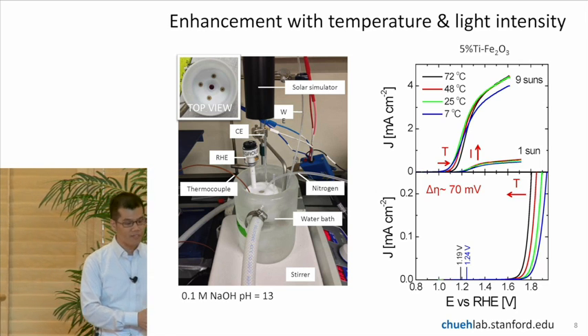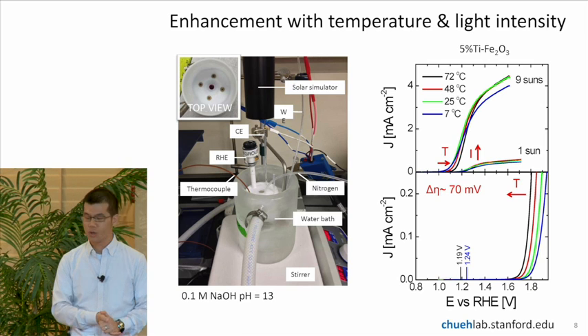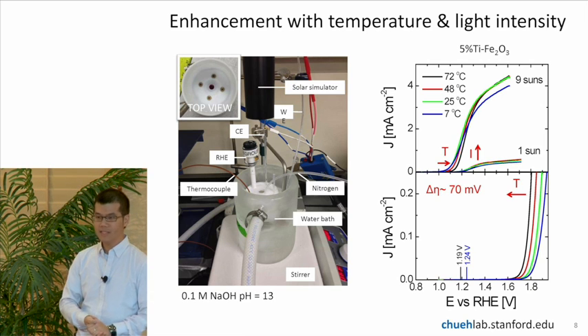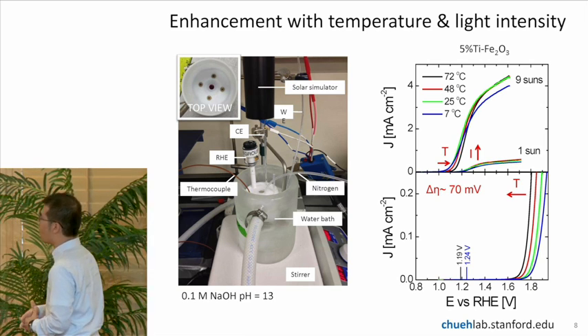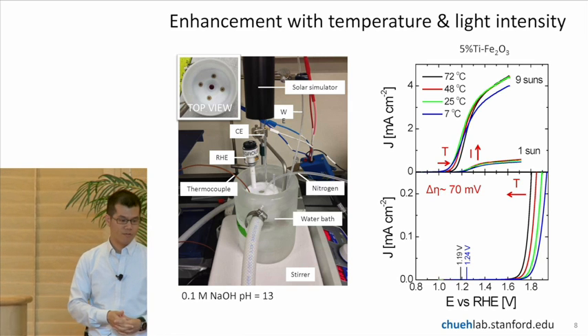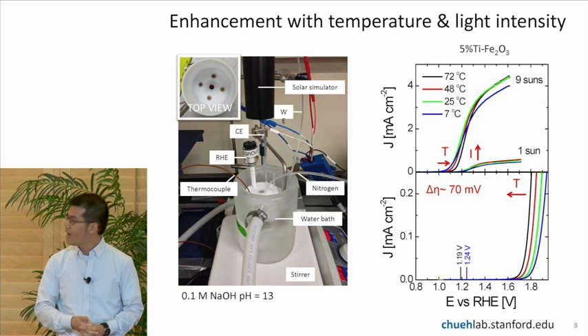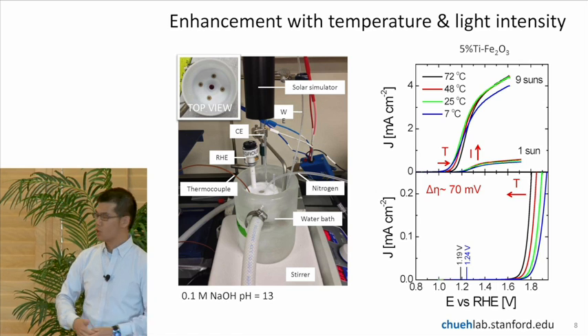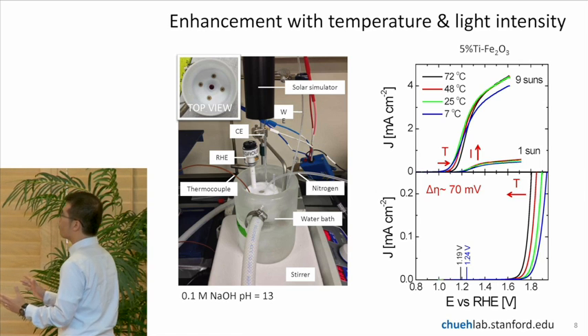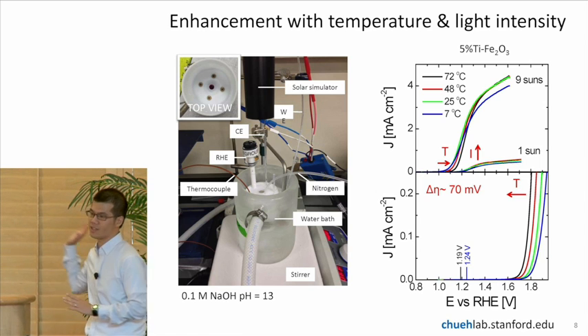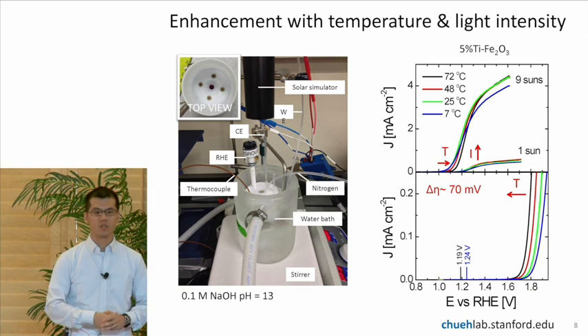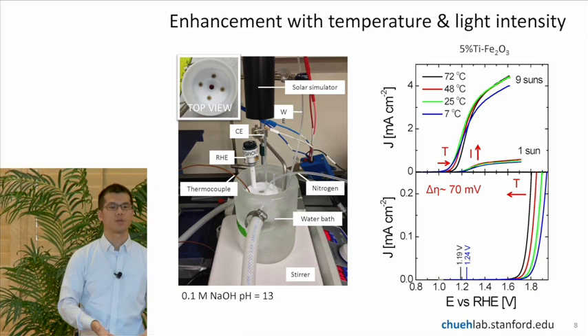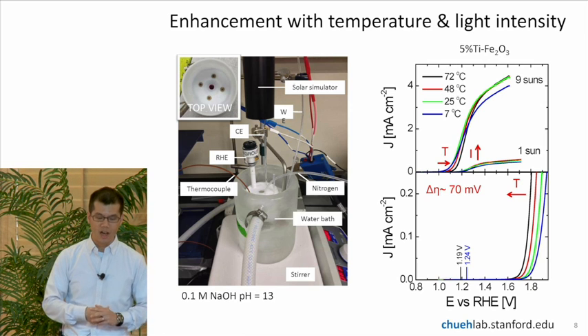So on the right, I have a couple of plots that show the performance of this material. On the top is what we call the IV curve, the current voltage curve under illumination. At the bottom, it's in the dark. So if you haven't seen this before, essentially we want to push the curve to the left as much as possible so it has sufficient potential to dissociate water into hydrogen and oxygen.